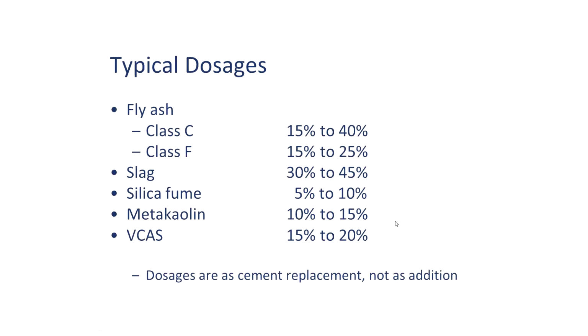And here are some typical doses. Now, different people use different doses, and you could do whatever you want, but these are the typical ranges. For VCAS, in my precast mix, I use 15%. I've gone down to 10%. I don't like to go above 15% because I'm starting to lose early strength. In GFRC, I use 20% replacement because I have all those fibers to help boost the green strength of the concrete. I don't have that in the precast.